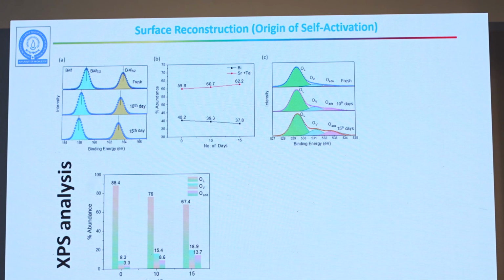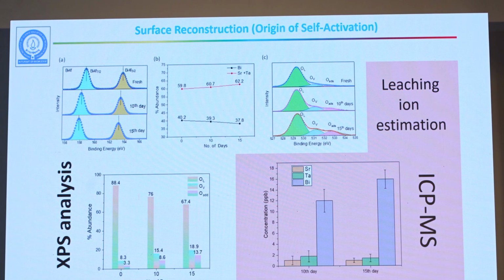So what we figured out is that why this happens is, again coming back to the same thing we discussed, we have a catalyst where we have bismuth oxygen bonds and other metal oxygen bonds. Now if you take into account all the different bonds, it is the bismuth oxygen bond which is the weakest. Now this oxygen and bismuth slowly start coming out from the surface. At this time, we have some pits on the surface which we call vacancies.